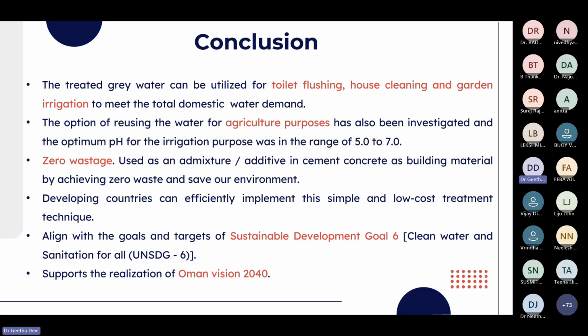So in conclusion, the treated grey water can be utilized for toilet flushing, house cleaning, and garden irrigation. We have used this treated water for agricultural purposes, especially irrigation, and we could see that the best result was obtained at pH 5 to 7. The remaining solid materials we have used as an additive in cement concrete, as an admixture in building material. That means zero wastage and saves our environment.